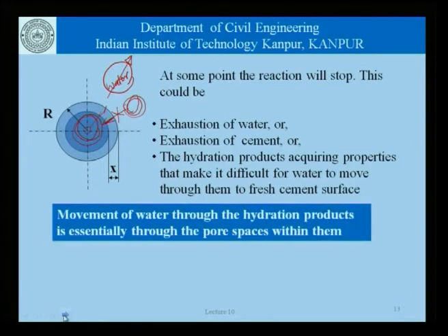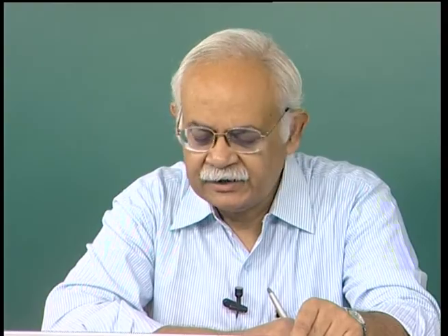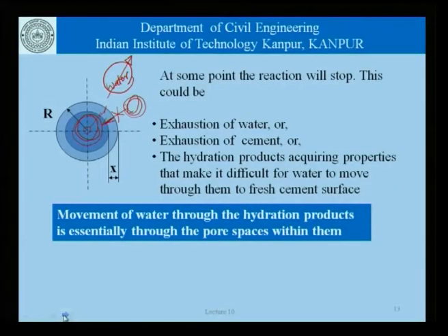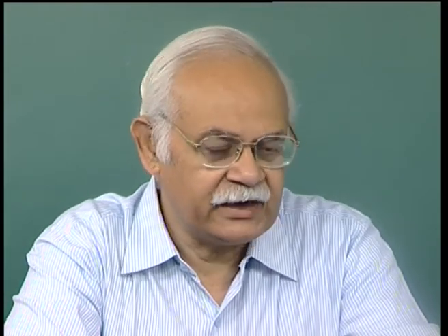Now, what this model brings out is the fact that movement of water through the hydration products is essentially through the pore spaces within them. How else would water move through hydration products? We have to have spaces between them, and these spaces are precisely the pore spaces within hydration products. The hydration products are not solid in that sense.